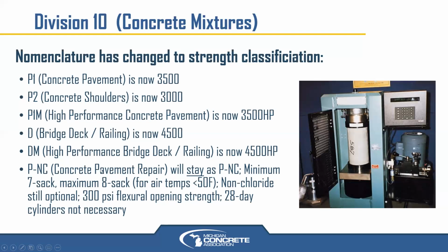One thing that is staying the same is your patching mixes. So for those road agencies that have concrete pavements that they're fixing with full depth repairs, P-NC is staying the same. The patching mix with non-chloride accelerator stays as that same code, minimum 7 sack with a maximum 8 sack only when you have air temperatures less than 50. Your non-chloride accelerator is still optional if needed to get the required strength. And that required strength stays the same, which is a 300 PSI flexural.